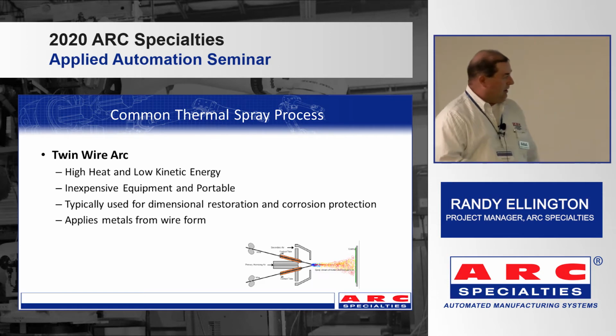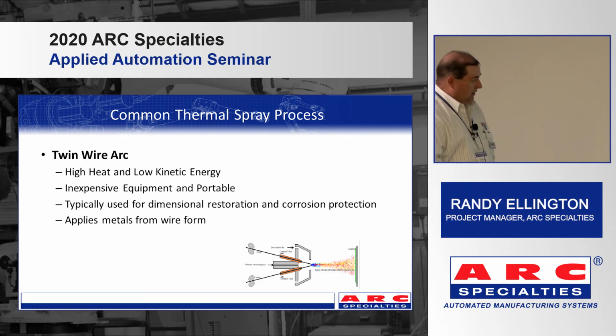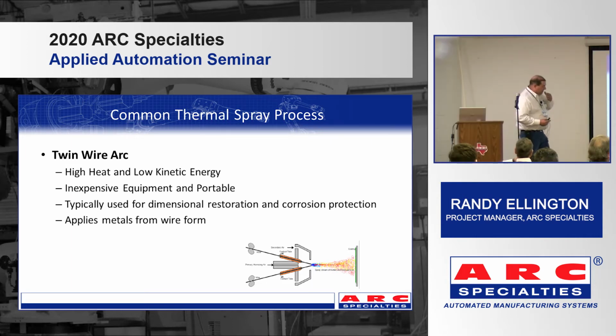And the other one I'll talk about is twin wire arc. This one, we'll say it's a high heat. It's nowhere near what plasma is, but here, instead of just heating the coating material to a plastic state, we're actually forming an arc. We're actually melting it. With most welding, you have a ground clamp on your work, and you have your electrode, and you're passing through. Here, we're actually putting positive voltage on one wire, negative on the other, bringing them together, creating an arc, and then sending compressed air through the center to atomize that and propel it at the surface.